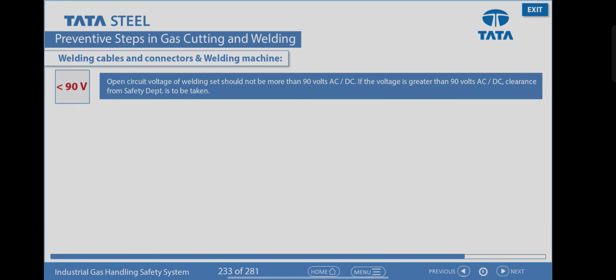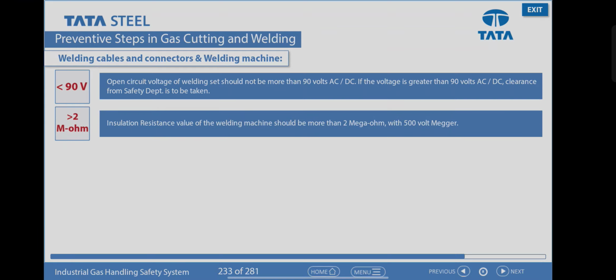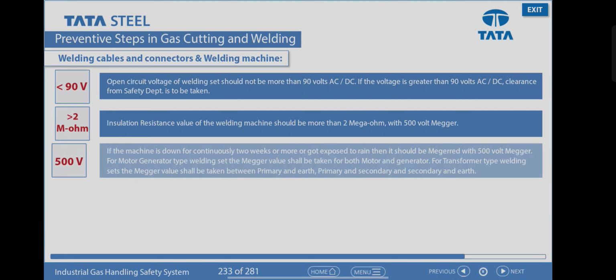Open circuit voltage of welding set should not be more than 90 volts AC or DC. If the voltage is greater than 90 volts AC or DC, clearance from the safety department is to be taken. Insulation resistance value of the welding machine should be more than 2 megaohm with a 500 volt megger. If the machine is down continuously for 2 weeks or more or got exposed to rain, then it should be meggered with a 500 volt megger.